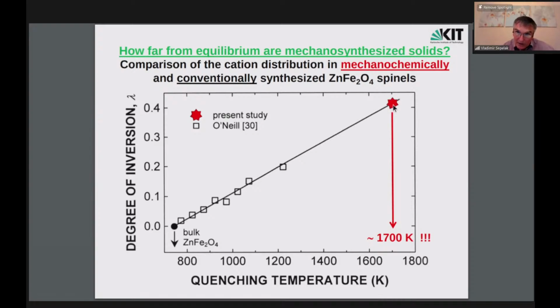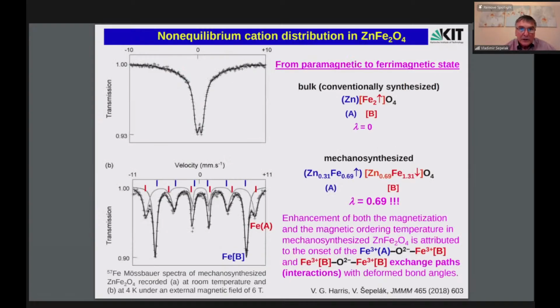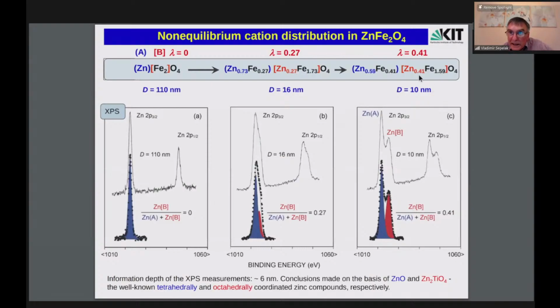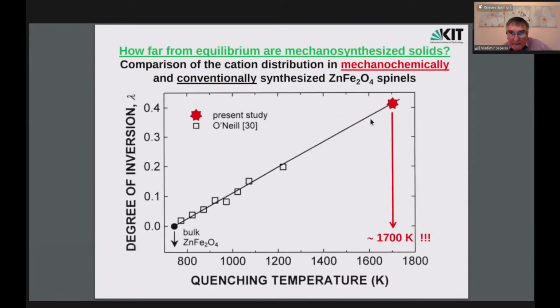You see that our data were obtained independently from various spectroscopic methods for this material. I presented X-ray photoelectron spectroscopy and Mössbauer spectroscopy demonstrating an inversion degree of 0.41. I can show you here. That means the zinc on octa sites concentration is 0.41, and we took this value, placed it on the line, and extrapolated that in our case the cation distribution corresponds to quenching from 1700 K. I do not know whether I answered.